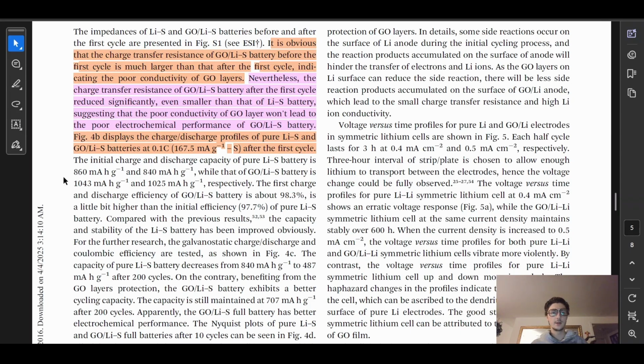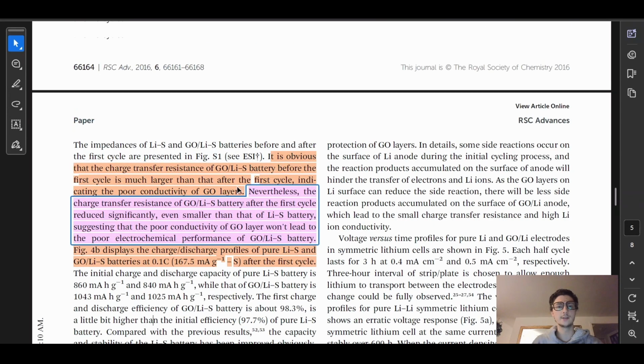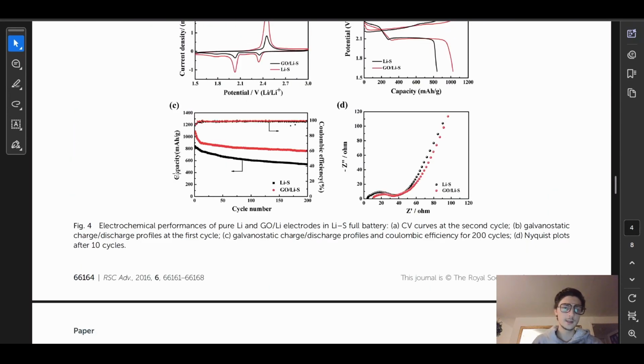The initial charge discharge capacity of pure lithium sulfur battery is 860 milliamp hours per gram and 840 milliamp hours per gram, while that of graphene oxide lithium sulfur battery is 1043 milliamp hours per gram and 1025 milliamp hours per gram, respectively. The initial charge discharge capacity, is that shown over here? Capacity here.